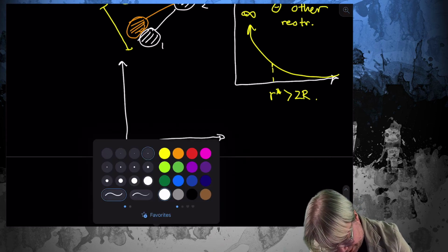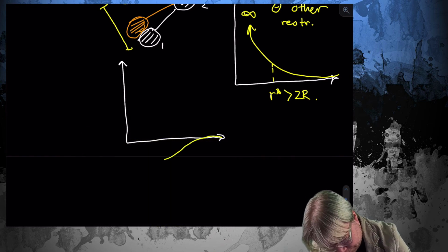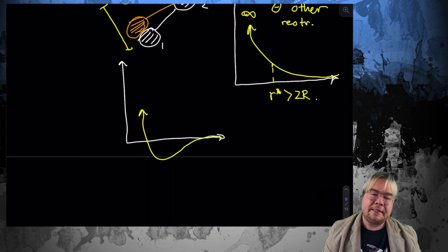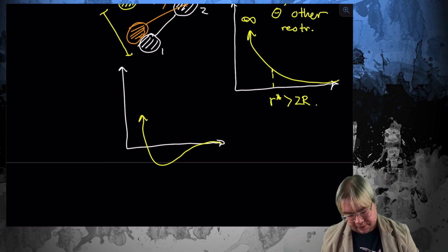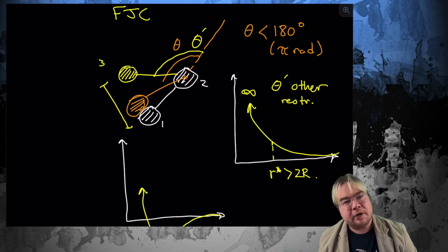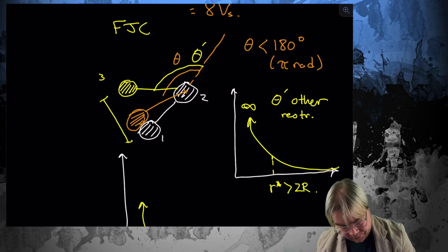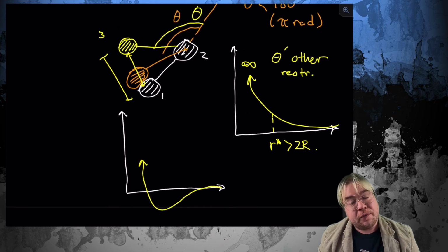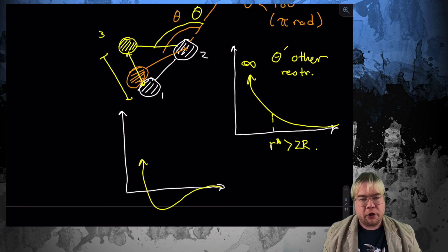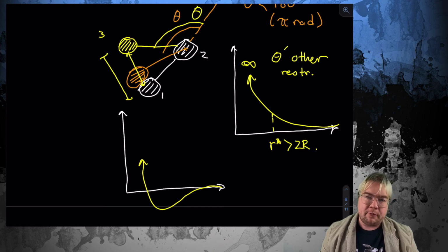So again, if there is an attractive potential like this, then it's going to bias it. It's going to prefer a certain distance between these. And that's really going to put another restriction on theta, right? Because you're preferring a certain distance between these monomers in that case. So that's the connection between excluded volume, interactions between monomers and their environment, and the size of a polymer chain.